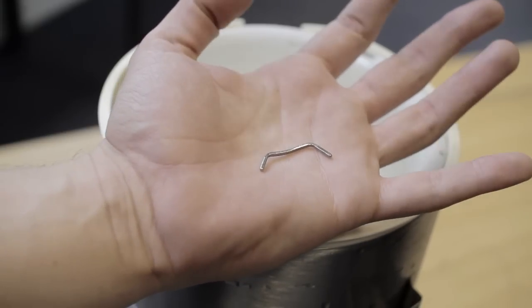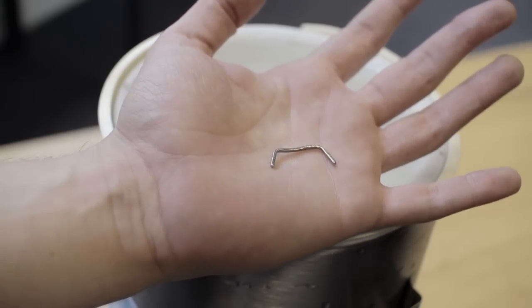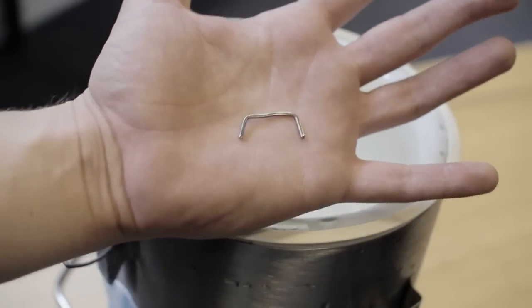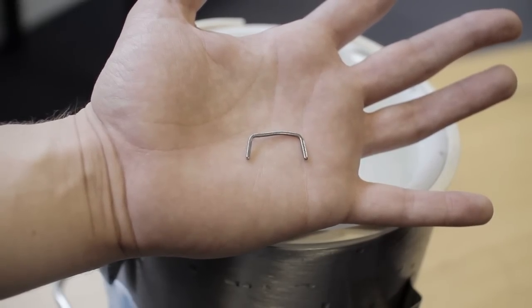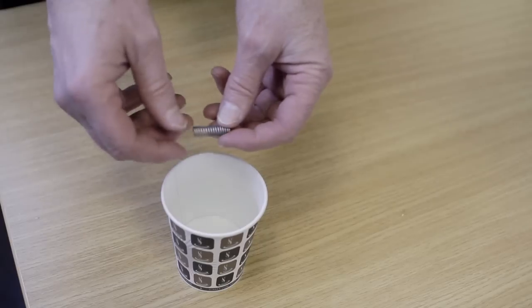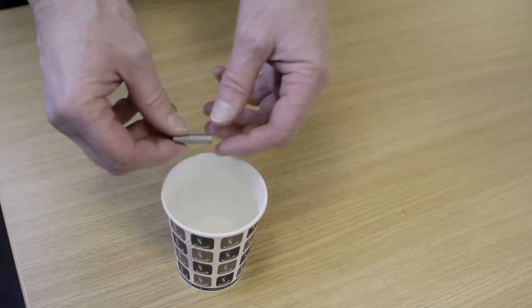So what's this used for? Well, it's designed for bones — fractures in bones. You put the pin either side of the fracture. You drill a little hole in your bone, pop one end in, put the other end of the staple in the other side, and then as it warms up, it closes the fracture site. One of the beauties of this alloy is that you can tune the transition temperature so that you can have the shape memory effect at any temperature you like, between about minus 100 to plus 100 degrees in this particular alloy, by just changing the composition of the alloy slightly.